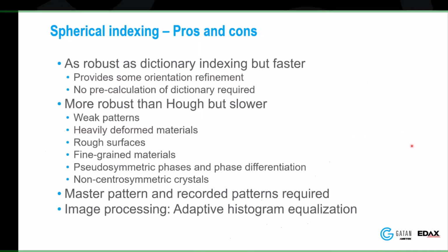So this whole spherical indexing approach has, for the most part, replaced dictionary indexing. It's as robust as dictionary indexing. It's faster. It provides some orientation refinement, and more importantly, especially for the geological side, there's no pre-calculation of the dictionaries. So if I was doing geological samples with 3, 4, 5 samples, these could be huge. Now, of course, it is more robust than the Hough, but it was also much slower. Well, I mean, it can be slower. Nowadays, it's actually pretty fast. I pulled this slide from elsewhere. I'm not sure I really believe all this anymore. It can be slower, but not always.